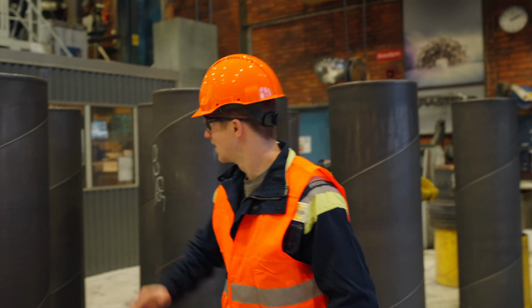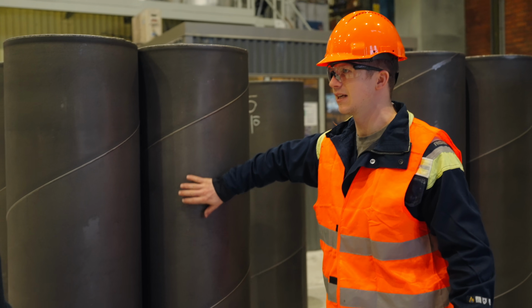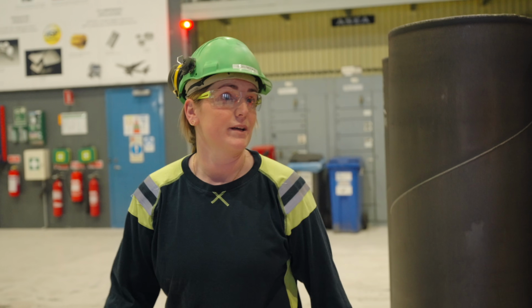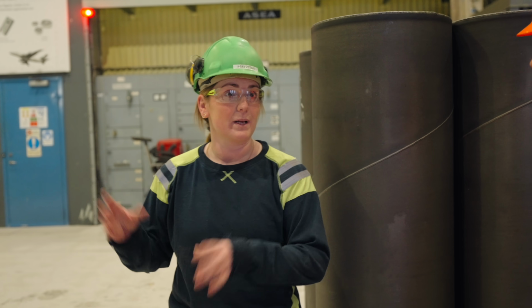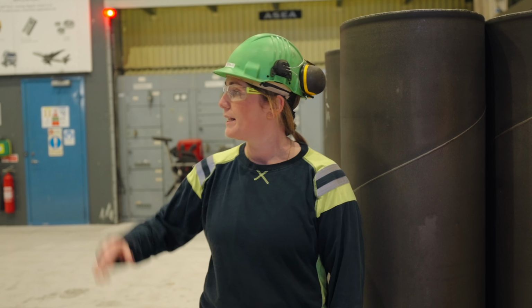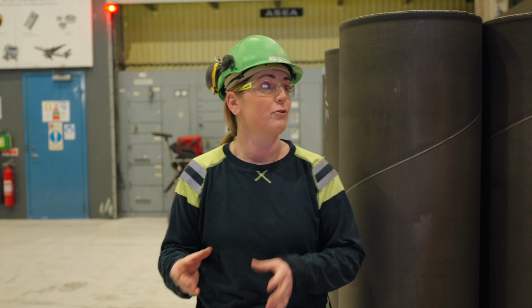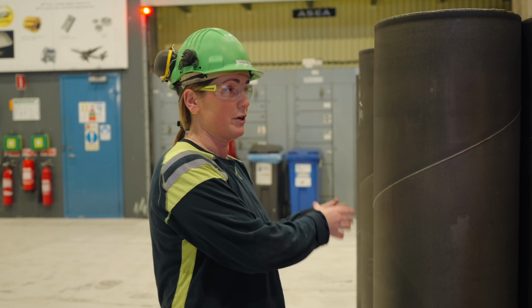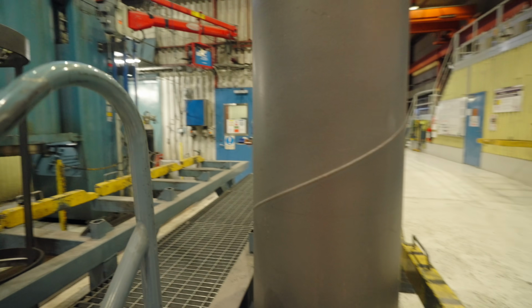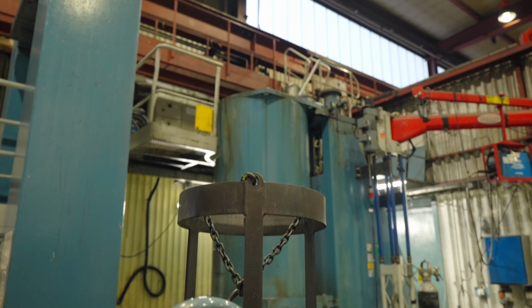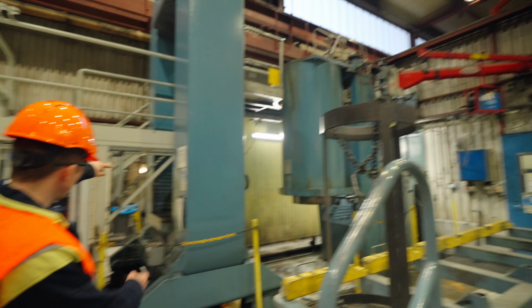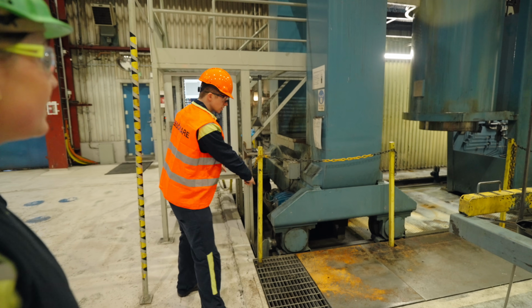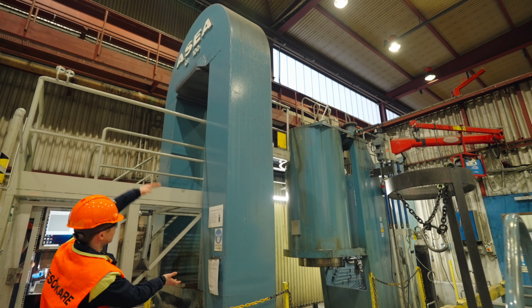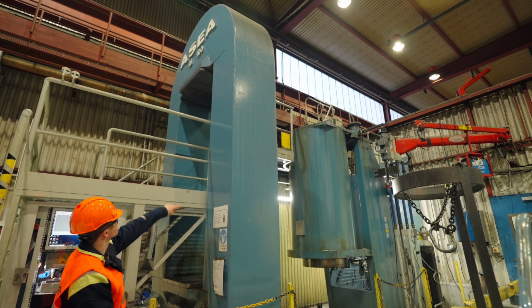Where does it start? You get this from the other factory? No, the start is over there. We fill the powder and we weld and everything. And then it comes here and we cold isostatic press the capsules before the preheating furnaces. These capsules go inside that tank of like a water-based emulsion. Yes. You put a lid on it. You then roll. Am I right in saying this is on rollers? That means that then you hopefully hold it tight because that's really strong. It's very tight.